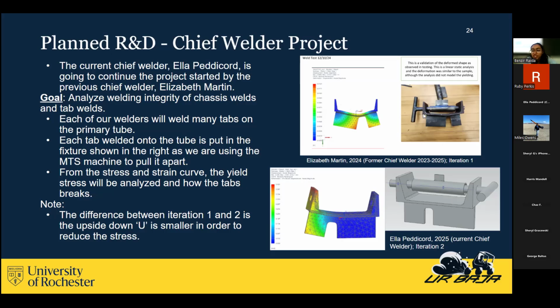So the idea was her little fixture design here would connect into the MTS machine, and then there is this rod that goes through the tube, and the other end of the MTS machine will hold onto the tab. The issue was that as they kept pulling on the tab, the actual fixture itself started to deform and stretch out. And when doing the FEA model, they did see there is this huge stress concentration around this U shape.